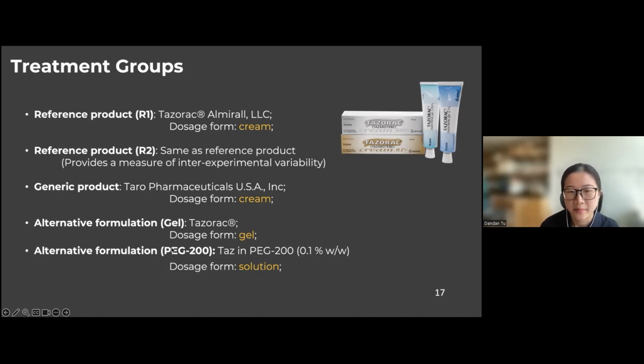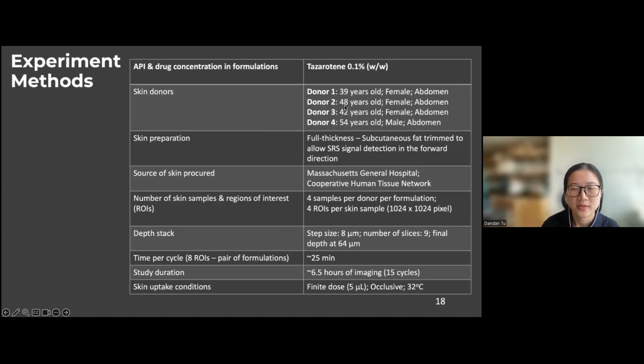The alternative formulations are added to have a group that should not be bioequivalent to the reference listed drug, because we use gel or PEG-200 excipient composed formulations. Those very different compositions should lead to different permeation behavior. And more experimental details, I will just briefly go through. The concentration we use for the study is 0.1%, and we have 4 different skin donors. For each imaging, we go to several different depths from the surface to 64 micrometers deep. The whole study duration is about 6.5 hours, and the skin samples are kept in a stage top incubator with temperature controlled at 32 degrees Celsius.